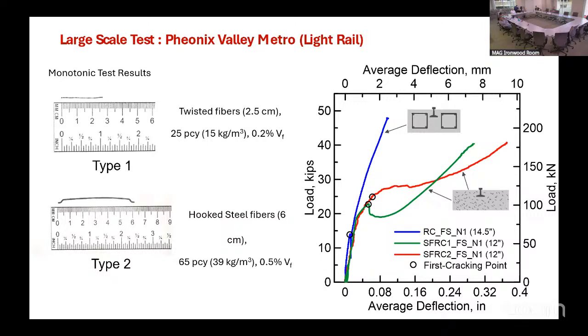So the load increases. The maximum deflection that we would get on a section is somewhere about 0.3 inch. But that's under load, and if you remove the load, the sample recovers at least half of that. So in 8 feet, you might have about 1/10 of an inch or so deflection after the section had cracked at twice the service load. So technically, this is going to stay. This is not going to fail at all. But this is a standard load that's applied.